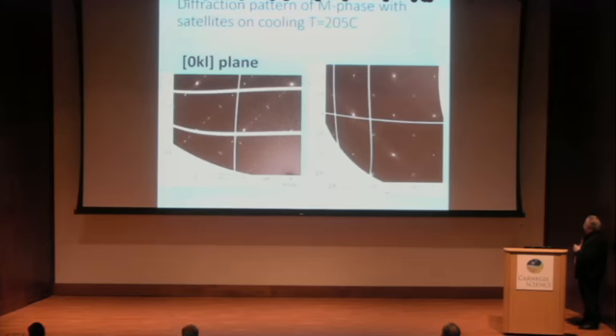But indeed, we have some complicated superstructure close to the zone boundary, close to the M point. We do have the sigma superstructure, the anti-ferroelectric one. We have an additional peak close to this sigma point, which is a kind of incommensurate or modulated structure. If we look at a one-dimensional cut, which is much more easily seen, so look here. At 1.5 there are weak satellites. I'll show them more exactly later. There is an incommensurate peak and there is the anti-ferroelectric one.